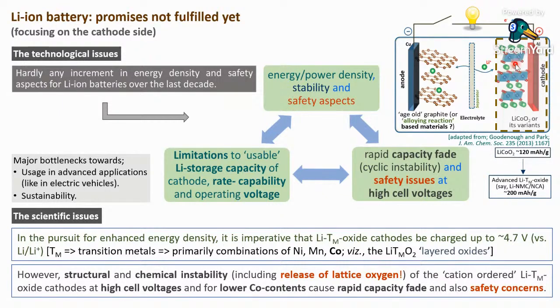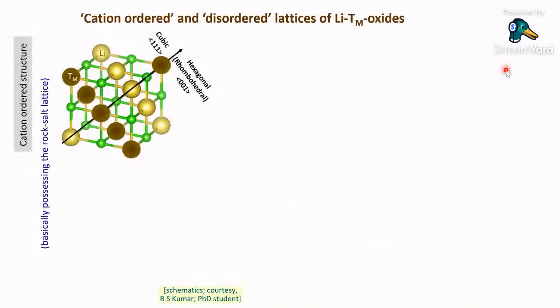And to do that, one needs to go higher and higher in the voltage range, and so one should be able to go beyond 4.3 volt, which is the present upper limit of the current generation lithium-ion cells, and maybe preferably go up to 4.7 volt if the electrolyte does not get decomposed at the same time. But going up to such a high potential does a lot of damage to the structure of the cathode material, and there lies the biggest problem.